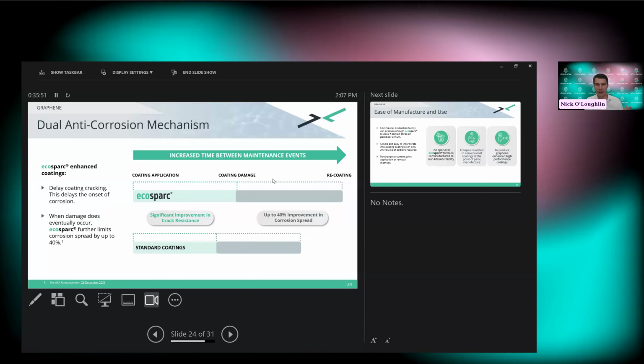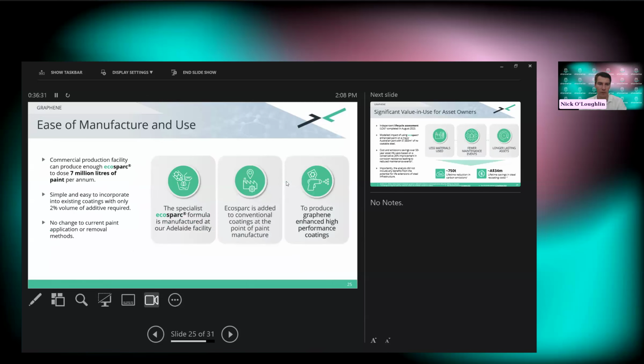It is mitigating the cracking of the coatings, and you get corrosion occurring when cracking starts. Alongside that, once cracking starts, and a lot of the testing we do in-house, which is to the ISO standards, the graphene also acts to limit the spread of the corrosion from that damage point. So there's a dual action there, and that leads to quite a significant benefit in terms of the durability of the paints. And we've got a variety of different results that we have produced, anywhere between sort of 20% up to 70% improvement. Typically, we use 40% as the sort of repeatable numbers. Yeah, excellent. Very easy to adopt, as I said.